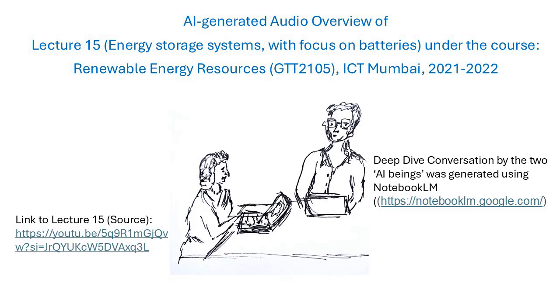Yoshino also made other crucial engineering contributions. Right, not just the anode material, the current collectors. Thin metal foils, aluminum on the cathode side, copper on the anode side, helps get the electrons in and out efficiently, reduces internal resistance. And the safety fuse, that sounds really important. Hugely important. It's a thin sheet of porous polyethylene plastic between the anode and cathode. So ions can pass through the pores normally. Yes. But if the battery gets too hot, say from a short circuit or overcharging, that polyethylene melts. The pores close up. And that stops the ions flowing, shuts the battery down before it can go into thermal runaway. Exactly. A brilliant, simple safety feature that really enabled these batteries to be used widely and safely in consumer